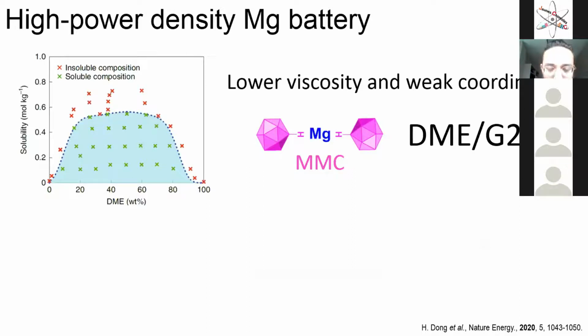Second one, you need an electrolyte that is low viscous and can do the job. I mean, can protect the surface of the metal magnesium from growing dendrites and all of this. And for this, you need to do a screening of the electrolytes. You just need to find an electrolyte formulation that would dissolve this magnesium salt and have a low viscosity and high ionic conductivity.